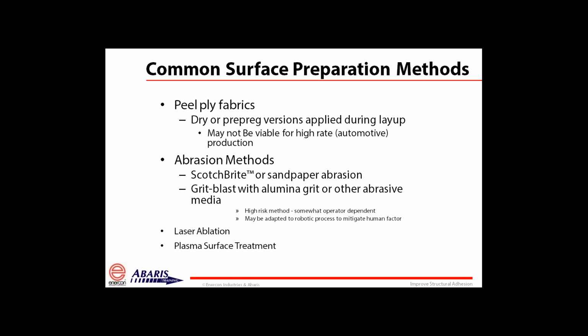With the Scotch-Brite, the risk of getting the nylon to melt on the surface can be seen when using high-speed tools such as a die grinder or other type of tool for trying to abrade the surface. And if you get too much friction at that interface, you'll actually melt the nylon into the surface and never get it out. So there are some downside issues associated with abrasion methods. Now, light Scotch-Briting of a previously pre-preg surface or a glossy surface is normally going to result in the best values. Sandpaper abrasion, depending upon what the substrate is, can give you highs and lows.